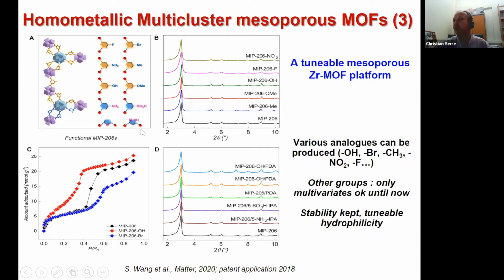And we could still introduce this ligand as a secondary ligand by using, for instance, the pure isophthalic compound. So, using what is called a multivariate strategy, which consists in combining 2 different ligands with the same geometry but different functional groups within the same solid. So it means that we can tune the surface of the pores of this MOF with all these functional groups.